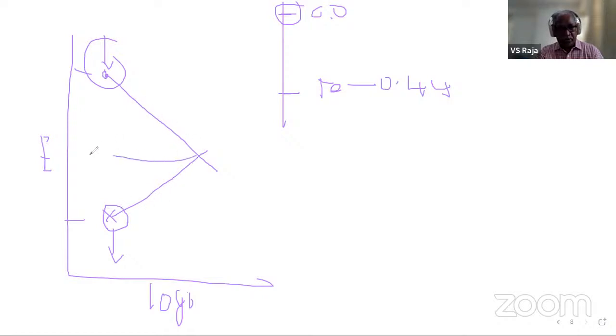And so you get E_corr and you get I_corr here. So the mixed potential theory tells you what will be the corrosion potential and what will be the corrosion current density for a given set of reactions, right? Of course, you must know the Tafel slopes, the exchange current density, and the equilibrium potentials. If you know them, you can in fact calculate. You solve the two simultaneous equations with the condition that the I for this and the I for this are the same, and E_corr is the same for both. You will be able to solve the equations. You get this value here.